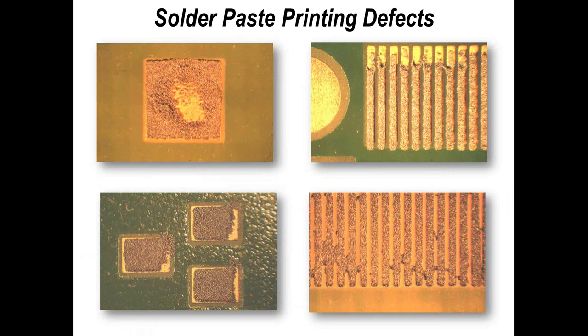So break it up into two or four, and then that reduces the amount the stencil is going to sweep into the aperture. On the top right, what's happened here is poor control of separation of the stencil from the surface of the printed circuit board. So we're getting a fairly decent print, but we're leaving some in the aperture. And it's consistency of separation, I would suggest, from the board surface. On the bottom left-hand side, you can see the same sort of things on SOT 23s, where the paste is not separating from the stencil cleanly on one side.